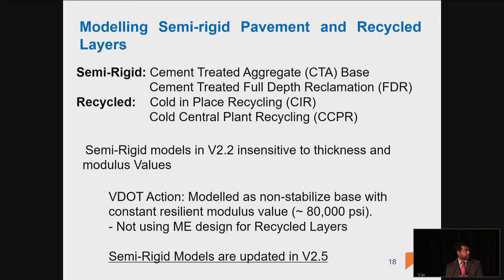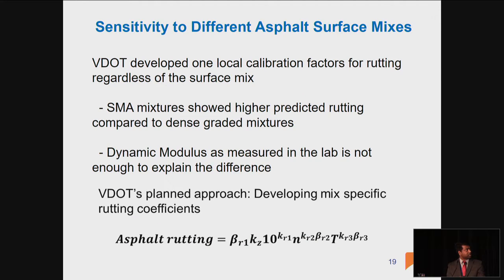For recycled sections, both cold-in-place recycling and cold central plant recycling, currently we are not using MEPDG. There's a challenge in using it because when you use both CIR and CCPR as a flexible layer, like Harold mentioned, Pavement ME is very sensitive to the air voids and the asphalt content. And the bottom-up fatigue cracking model uses the bottom layer, so in this case, it will be a CIR. In the field, usually you get higher air voids for the recycled section, so you have to be careful when inputting.